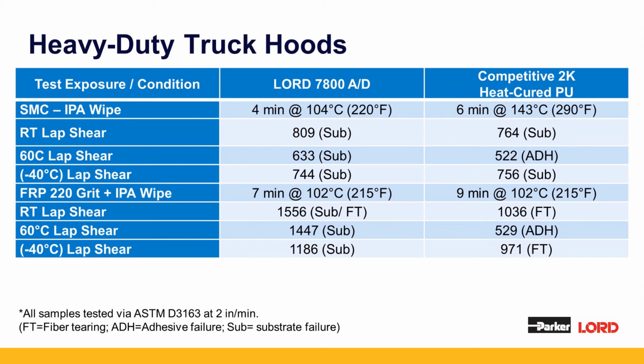One of the concerns, however, they had was with the FRP, the gel coat on the surface was subject to degradation due to heat. So there was a slower process associated with the FRP and a lower temperature. So looking at this one, we used the competitive adhesive, we used the Parker Lord 7800. What we were able to achieve is taking about 2 minutes out of the manufacturing time for the SMC with heated tooling, and we also lowered the temperature by 70 degrees Fahrenheit.